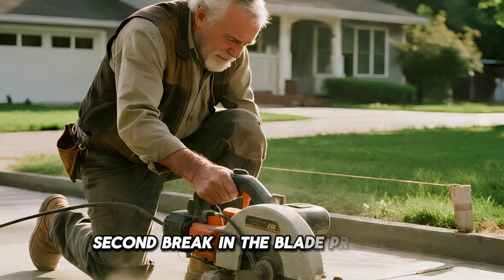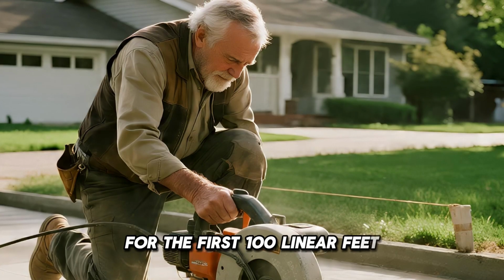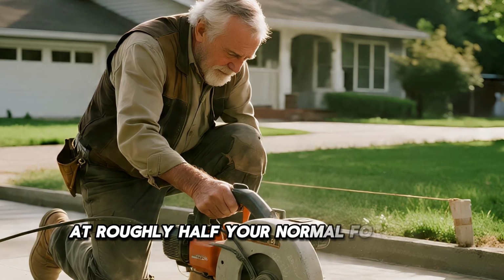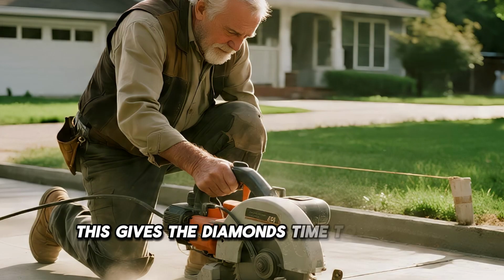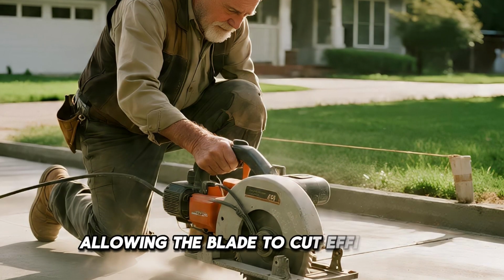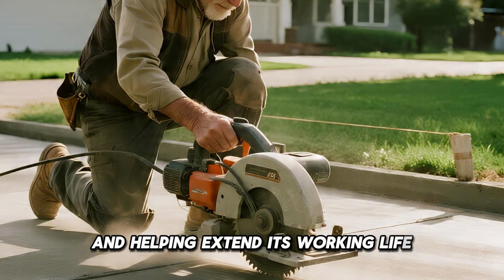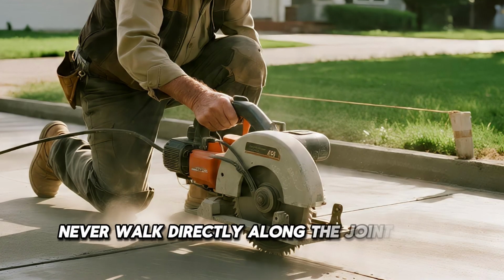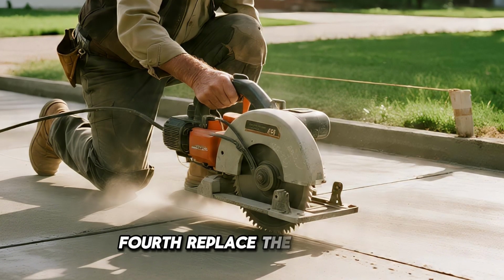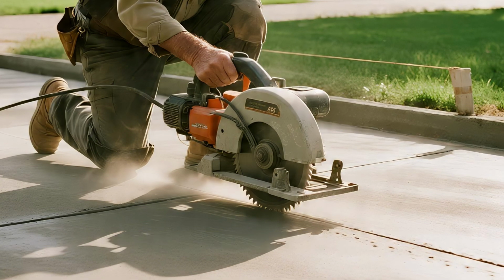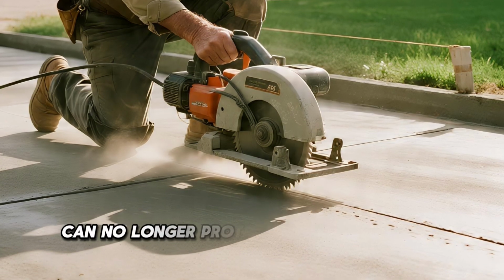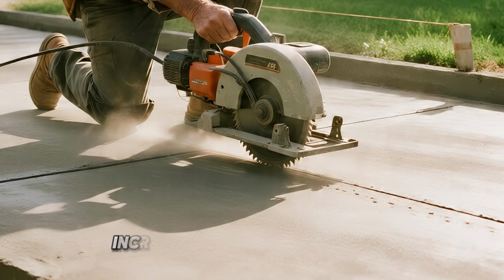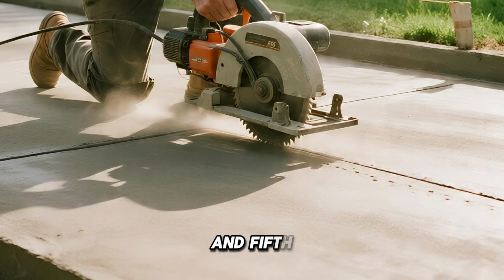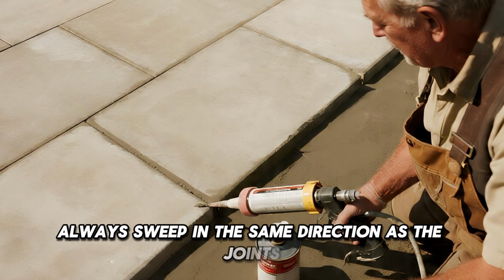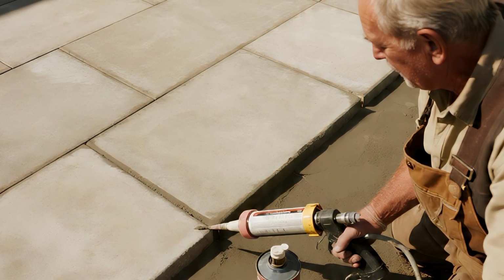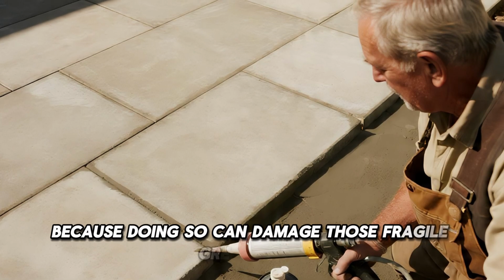Second, break in the blade properly. For the first 100 linear feet, operate a new blade at roughly half your normal forward speed. This gives the diamonds time to expose correctly, allowing the blade to cut efficiently and helping extend its working life. Third, never walk directly along the joint lines while cutting. Fourth, replace the skid plate whenever you replace the blade. A worn skid plate can no longer protect the delicate joint edges properly, increasing the risk of spalling. And fifth, always sweep in the same direction as the joints. Never sweep across fresh cuts, because doing so can damage those fragile green edges.